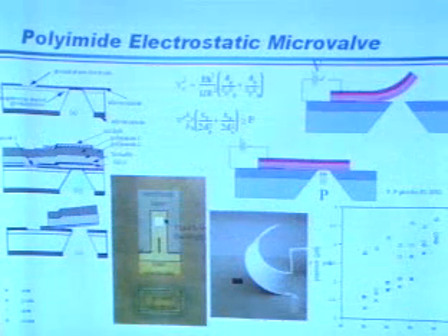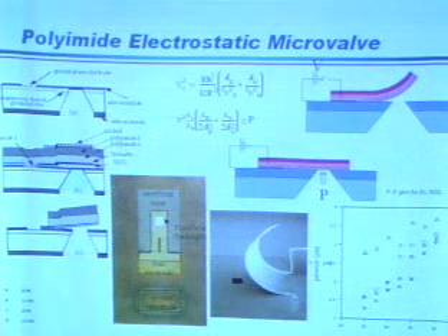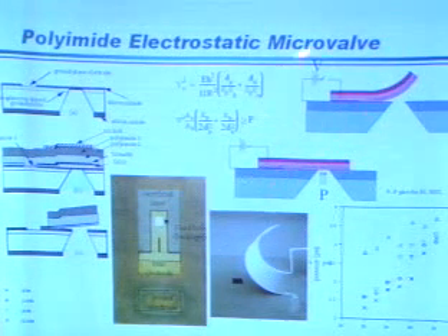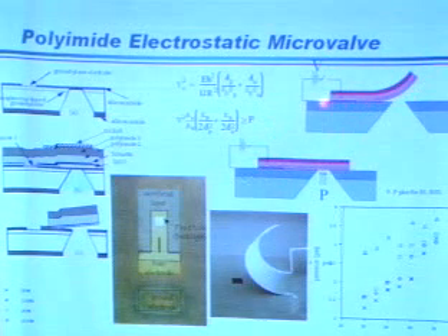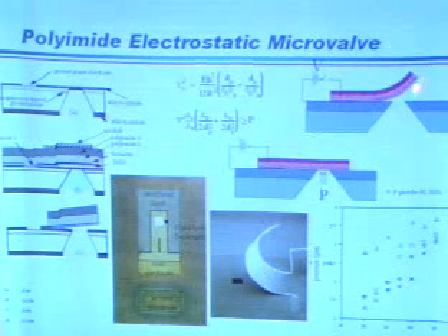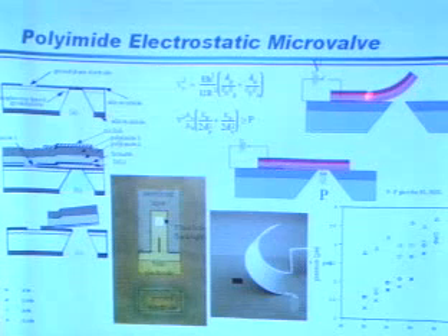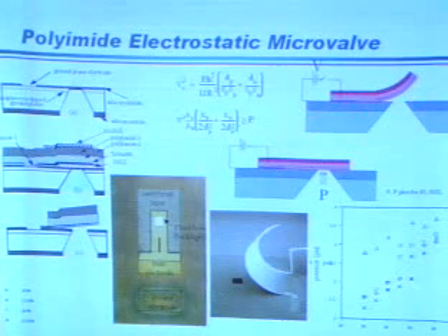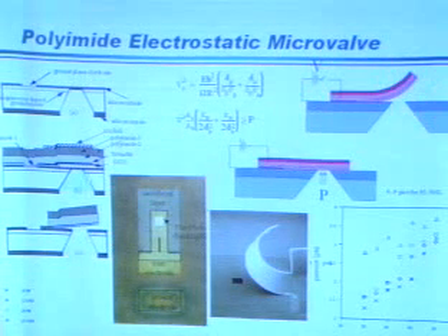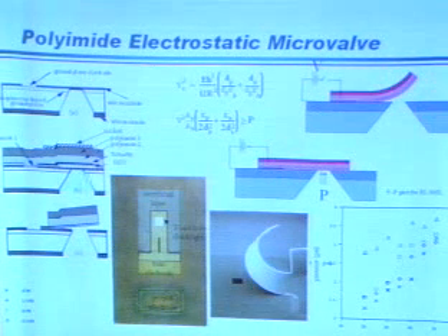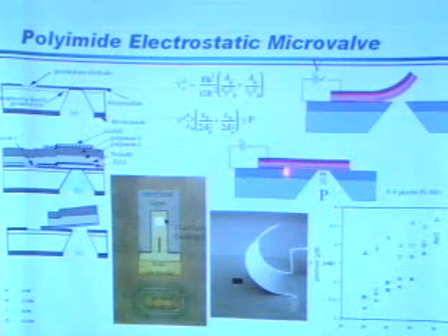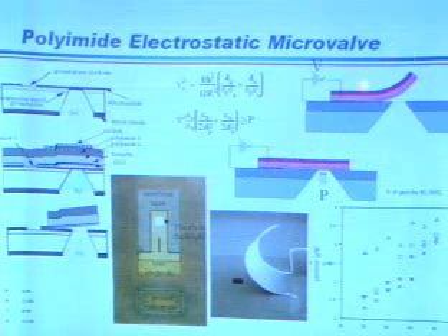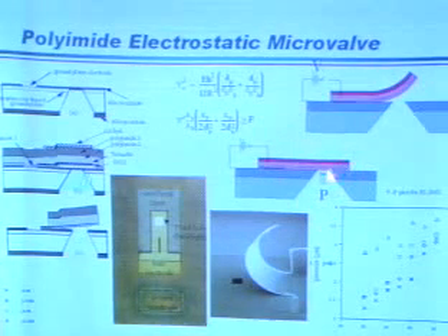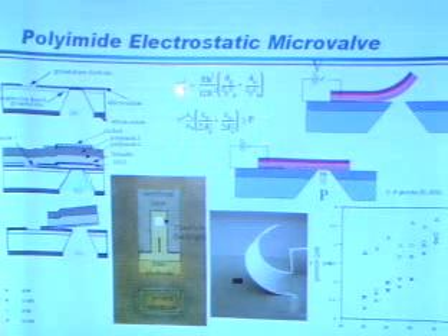One application of using these thermal bimorphs that gives you large deflections with polymers is a microvalve. You could embed inside the first layer a metallic layer, which gives you a well-defined gap between that electrode layer and the top of the substrate, which are both conductive, and you apply a bias voltage. This allows you to zip up the normally open valve with a critical voltage that overcomes the mechanical stiffness, and the pressure will be held off. With the critical voltage calculation, you can get pressure hold-off here.